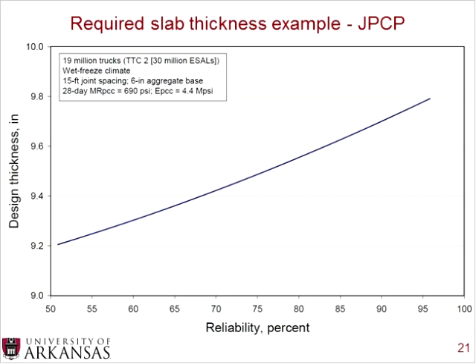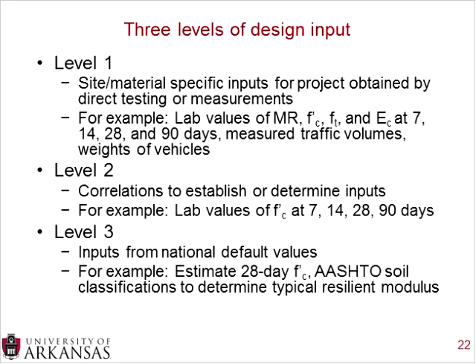Or if you want to go down to a reliability of only 50%, it would be a thickness of 9.2 inches. Now, sometimes the reliability range gives you a greater thickness design, depending on the materials, depending on the climate. This is a relatively narrow band, but you can see as you increase your reliability in general, you do increase your thickness.